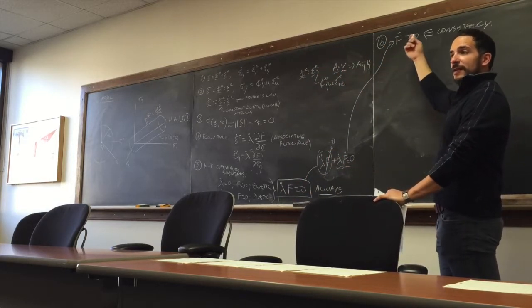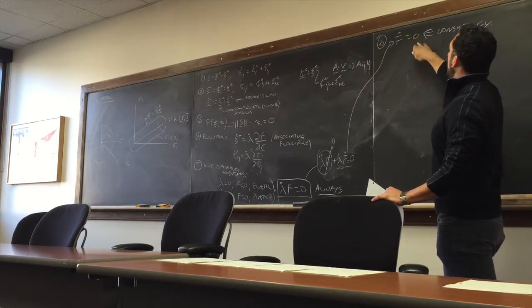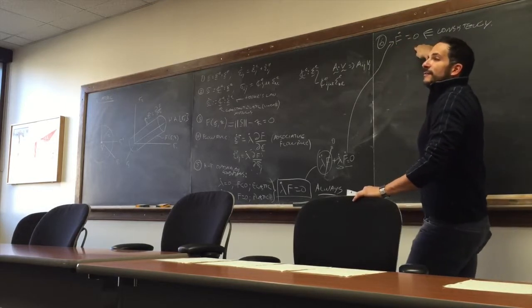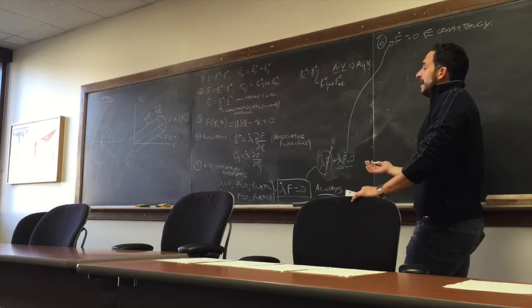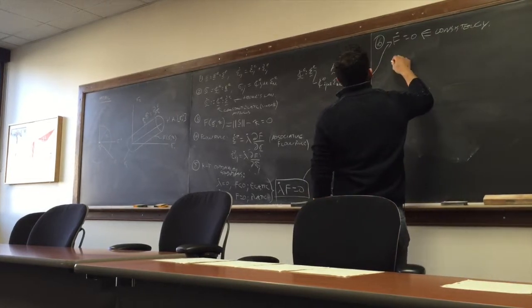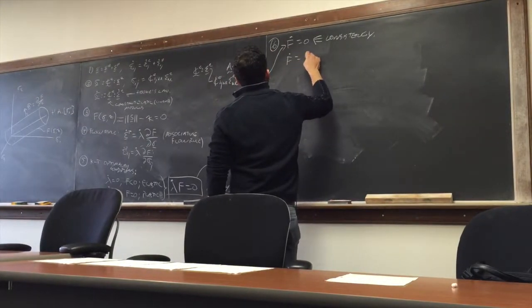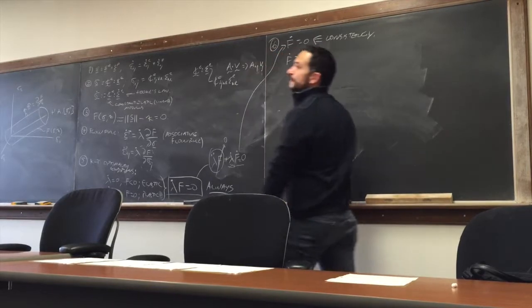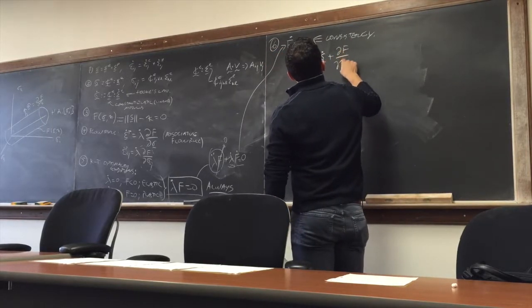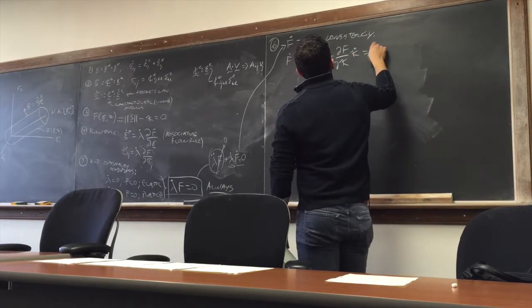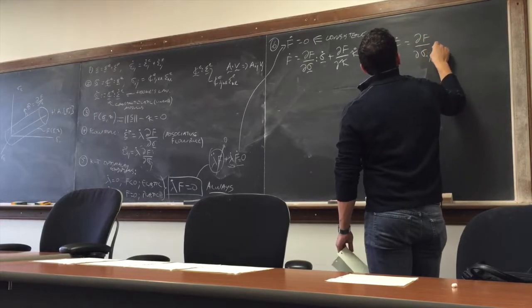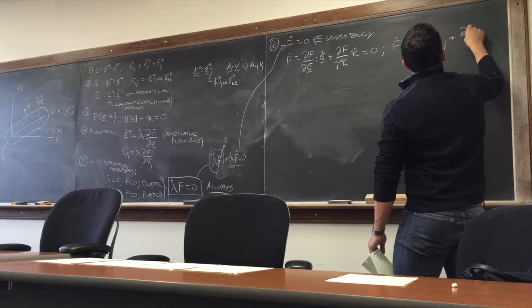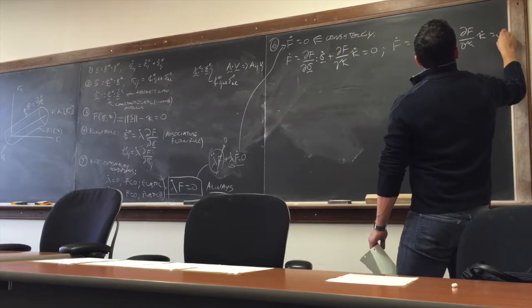And that's where the consistency condition came in the 1D case. In the 3D case, same thing. So now, in all models, you're always going to play with this idea of f dot equals 0 to try and find lambda dot. I'm going to call that a plasticity complete problem, in the sense that once you find lambda dot, you found everything. Okay? So let's do that. So f dot now is equal to, by the chain rule, dow f dow sigma double contracted with sigma dot, plus dow f dow kappa times kappa dot equals 0. Or in index notation, f dot equals df d sigma ij sigma ij dot plus df d kappa kappa dot equals 0.